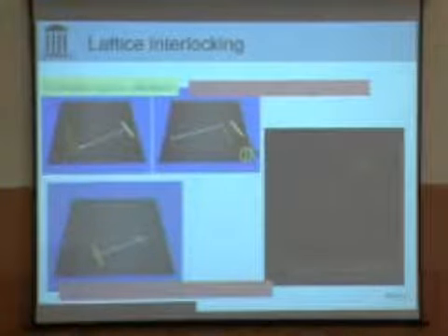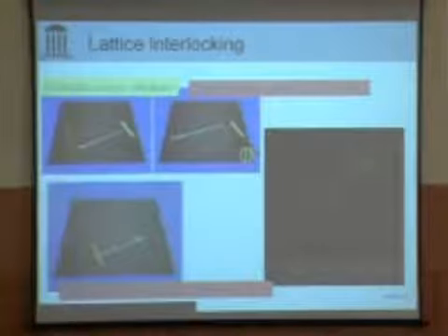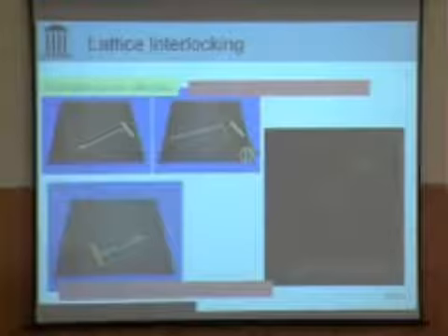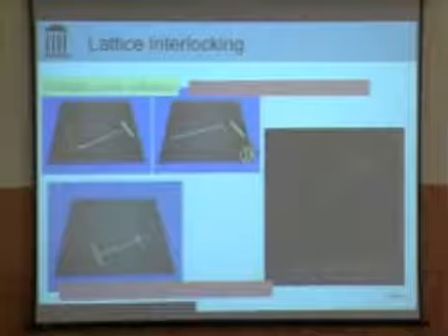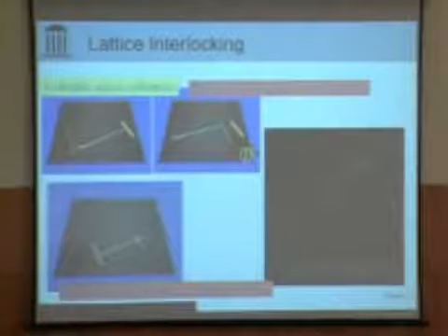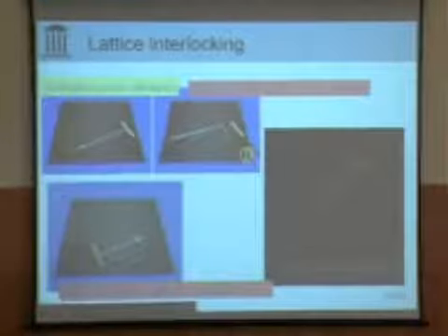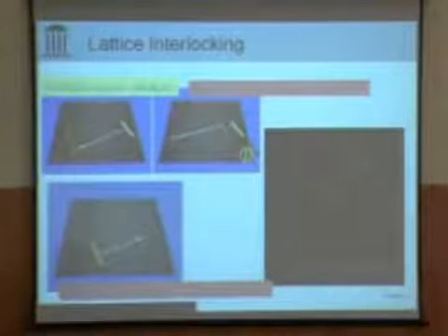They roll. And in fact, if you start off with one nanotube here, the other nanotube here, you take the tip and you push on this one, it'll roll, hit this one, and then both of them will roll across the surface with one nanotube making the other nanotube roll. And that's evident here in the force. Here's the force of making one nanotube roll. Here's where it hits the second nanotube, and both of them roll together.